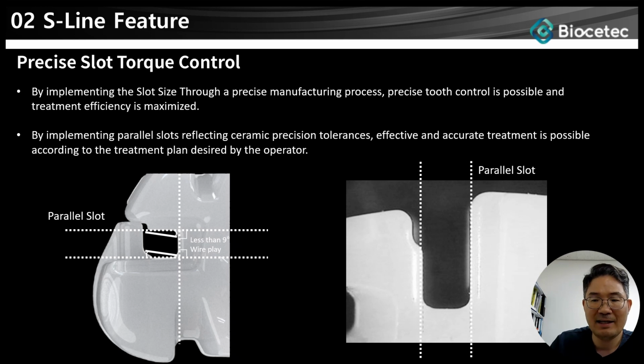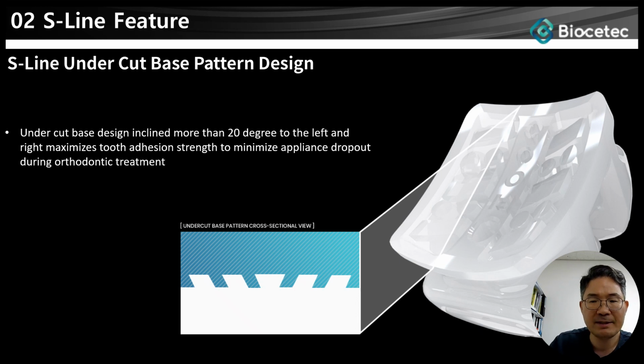And the S-line has a precise slot size and parallel slot like this. So S-line has a precise slot and less than 5 degrees of wire play when 19x25 wire is inserted into the 022 slot, which is very predictable torque play. And also the undercut base design with a mechanical locking structure is the strong point of S-line, and more stable bonding strength, and which has undercut base pattern inclined at a 20 degrees inclination angle like this.